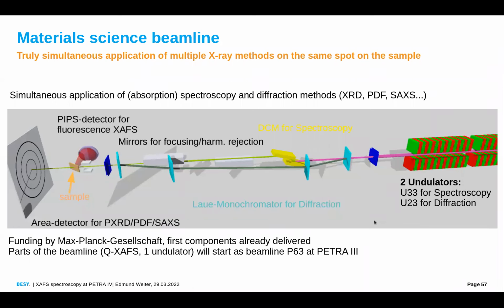It will use two undulators to do diffraction and spectroscopy at exactly the same time on the same spot. So we get the radiation from these two undulators. One undulator produces high energy X-rays for the diffraction, and the other one, well, the X-rays which we need depending on the edge, and this one will be scanned. The one for the spectroscopy changes the energy, and then a Laue monochromator is used to bypass the XAFS monochromator for the high energy for the diffraction, and later to reunite the two beams on the sample, and then you can do diffraction and XAFS at exactly the same time on the same spot.